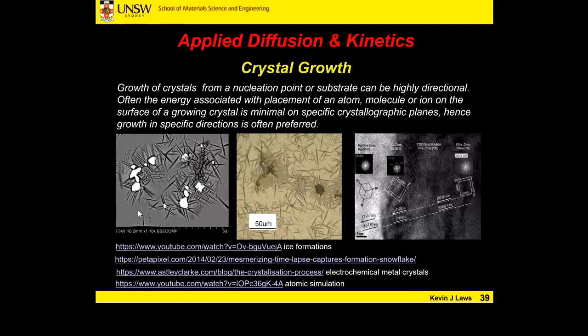What we've done in these materials is add a ceramic particle to our melt, liquid alloy. This is Y2O3, yttrium oxide. It doesn't melt within our alloy melt, it just stays there as a particle. We can stir it in. And then we rapidly cool this melt. What we produce is a microstructure where we've got this amorphous matrix, so this is a glassy metal here, no crystalline structure whatsoever, this light gray phase.